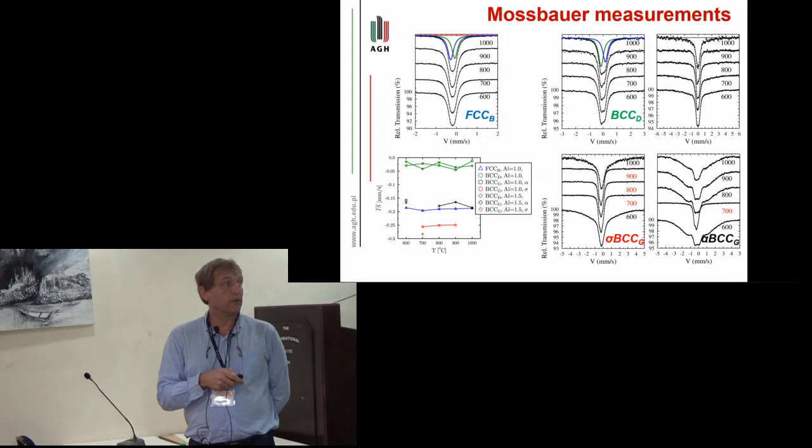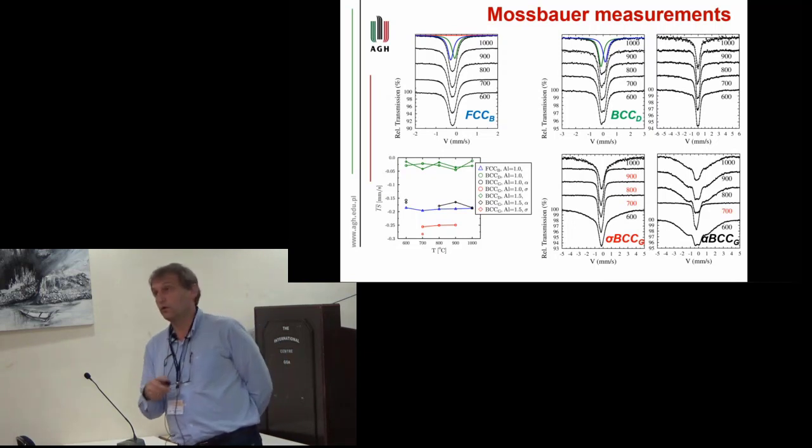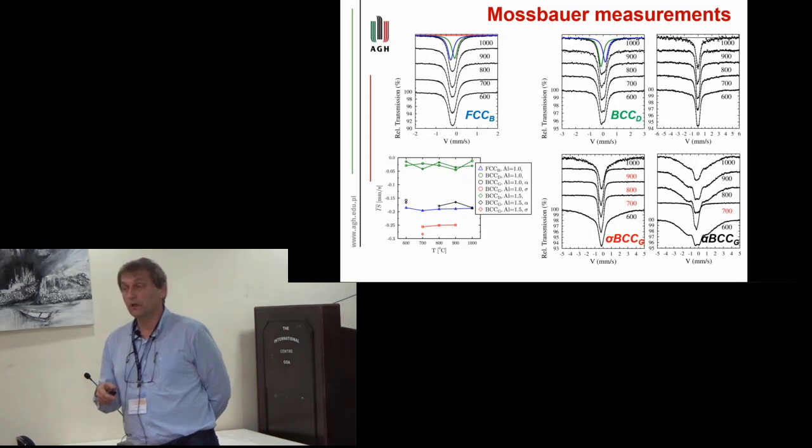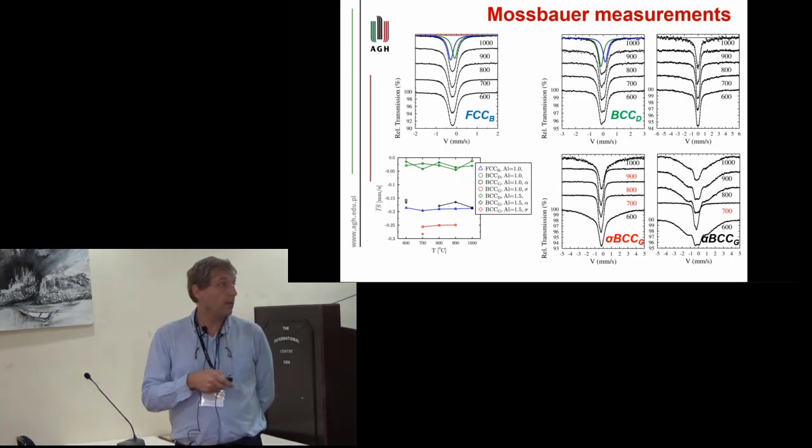BCC dark phase changes a bit its nature—some magnetic splitting appears. And we are explaining that in terms of spinodal decomposition in the sample.